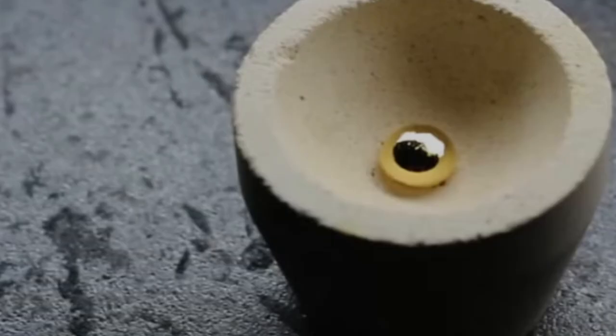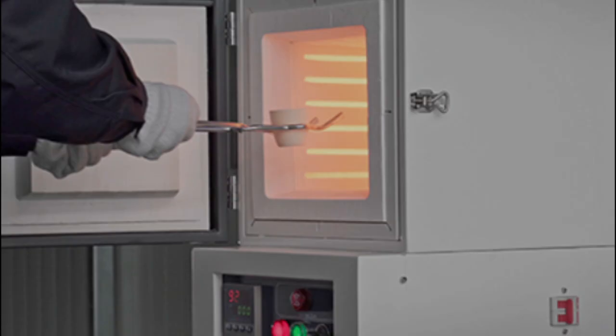It works by placing the alloy of precious metals with lead or bismuth and base metal impurities into a dish made from bone ash, magnesium oxide, or Portland cement. The alloy is then heated in a furnace where it melts and, exposed to hot air, oxidizes. More precisely, base metals in the alloy oxidize and absorb into the cupel. Silver, gold, and the rest of precious metals that do not oxidize are left as a small bead at the bottom of the cupel.